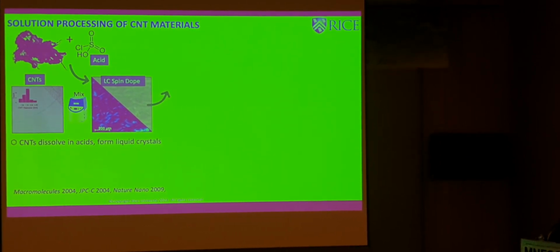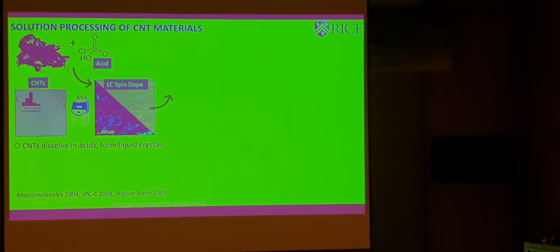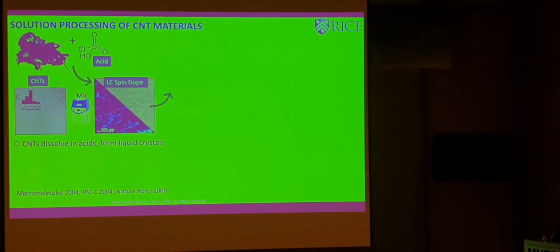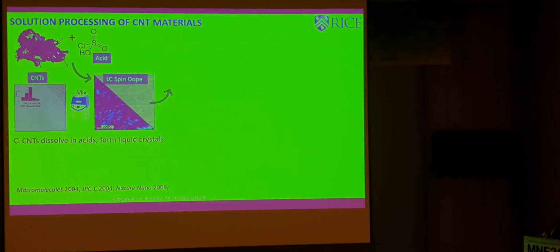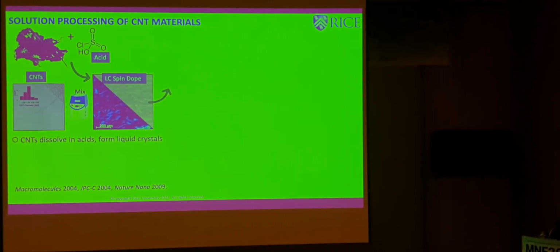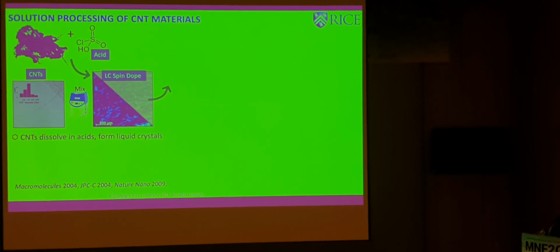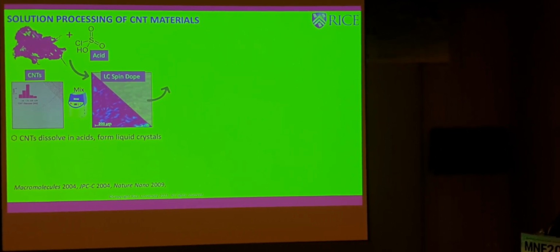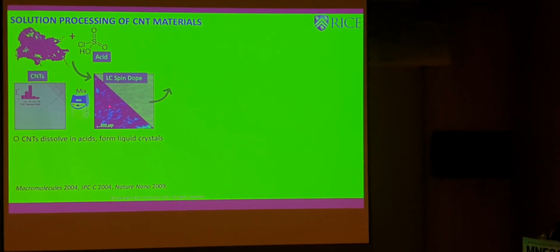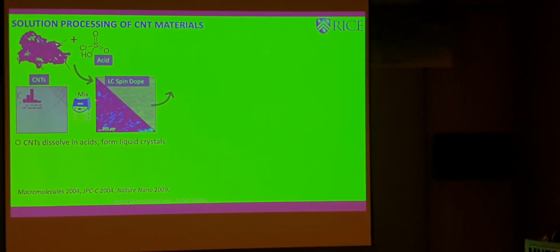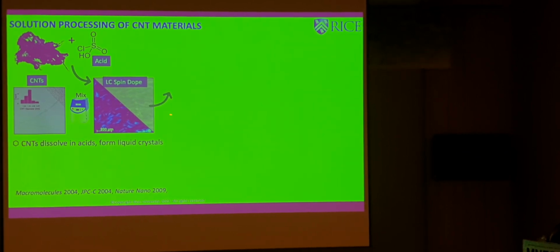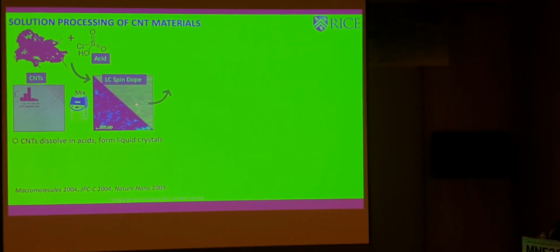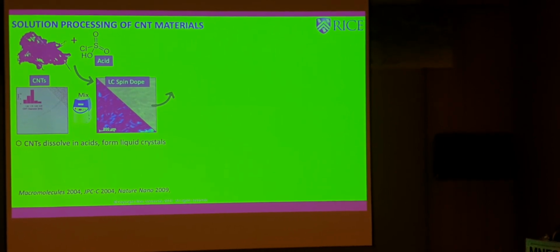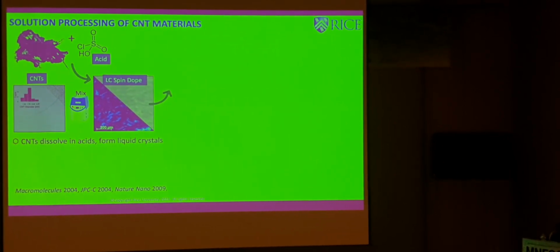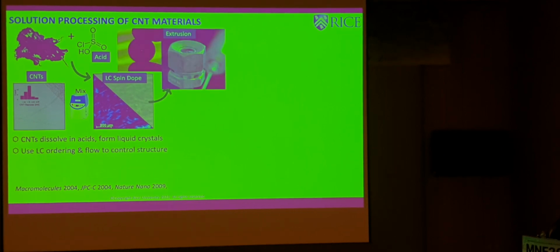And we used acids, because acids were known to protonate stiff polymers. And in fact, they've been used for Kevlar and PBO. And so it turns out that if you take nanotubes, put them in an acid, chlorosulfonic acid works better because it's stronger. You can use other acids. You can see the formation of liquid crystals. That's the same image in transmitted light, where you see just a little bit of non-uniform concentration. But then in polarized light, you see domains that turn on and off, and those are your liquid crystals.